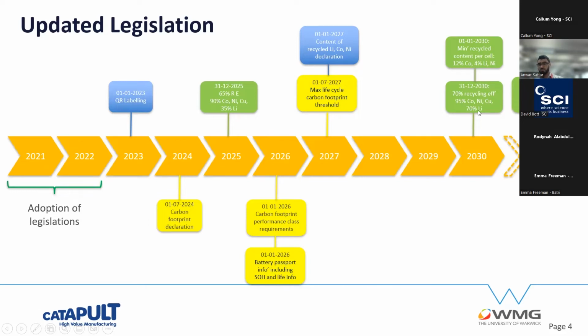More interestingly, however, in 2030, they're going to introduce a new concept, which is you have to have a recycled content of material per every cell that's made. So it's 12% for cobalt, 4% for lithium and nickel. And then in 2035, that increases. And you can see there what it increases to.